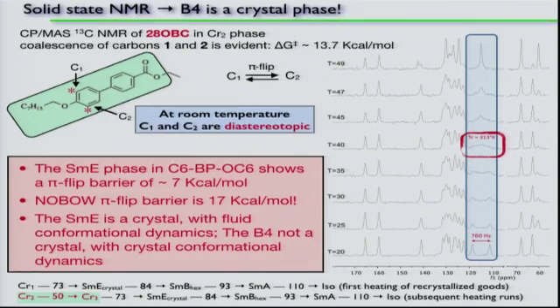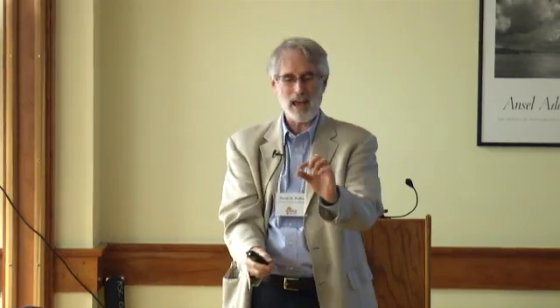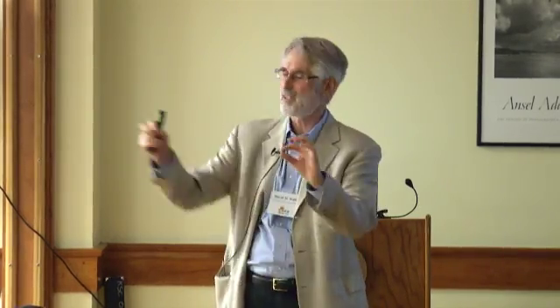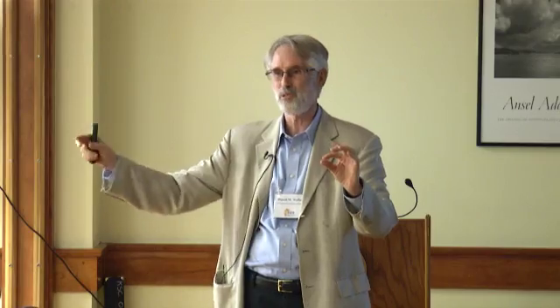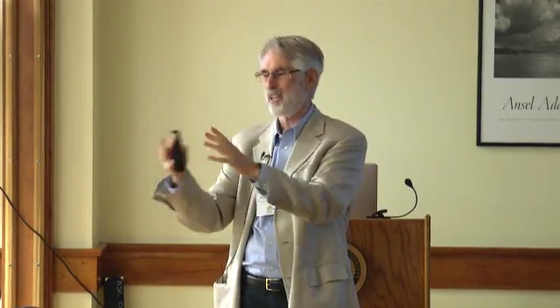And that nucleus, you have subcritical nuclei that grow and shrink and grow and shrink, and then a nucleus gets critical and whammo, the thing grows really fast. This is very typical in crystals in the solid state. Okay? And so I think that's what's happening with the helical nanofilament. So you see that big right-handed domain. Well, that all came from an original right-handed nucleus, and then somewhere else a left-handed nucleus nucleated and started growing. And the rate of growth versus the rate of nucleation determines the size of the domains.